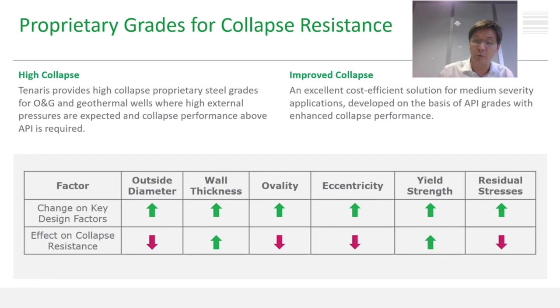Yield strength is a parameter that will always contribute positively to the collapse performance. By increasing yield strength, we will increase the collapse resistance. There are certain limits given by the standards or by the specification, but as a manufacturer, we can move inside the limit, trying to maximize the yield strength value and hence provide a better collapse performance. The last element is residual stresses, which also contribute significantly. A high residual stress presence will compromise the collapse performance. By controlling the operation, in particular by making sure that straightening happens at hot temperature, we can reduce the residual stresses, hence providing a positive effect on collapse resistance.